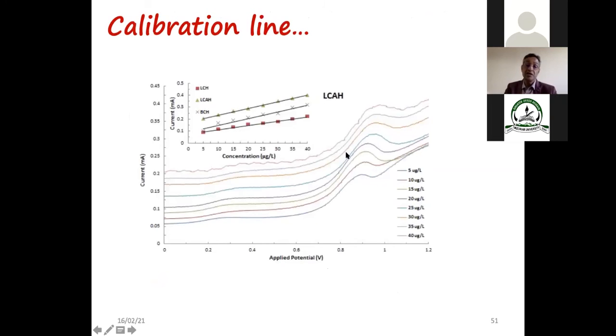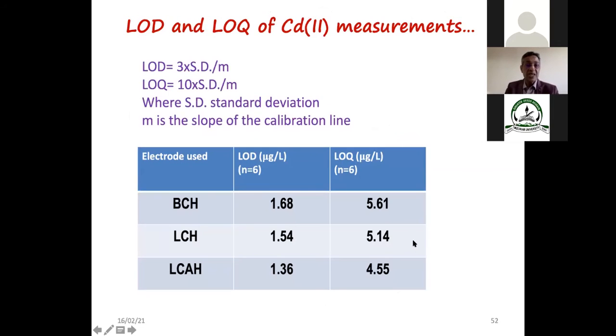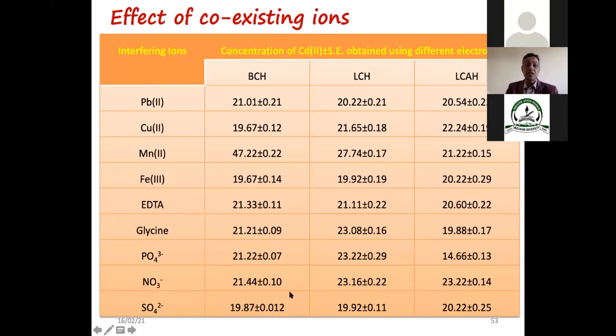Here, you can see that a very good calibration line has been observed when we varied the concentration of cadmium from 5 to 40 ppb. With the help of this, we calculated the LOD and the LOQ values. LOD was obtained as 1.68, 1.54 and 1.36. These are for the modified materials only, so a very low LOD value was obtained for cadmium-2.